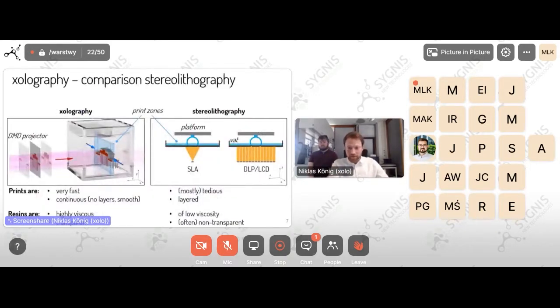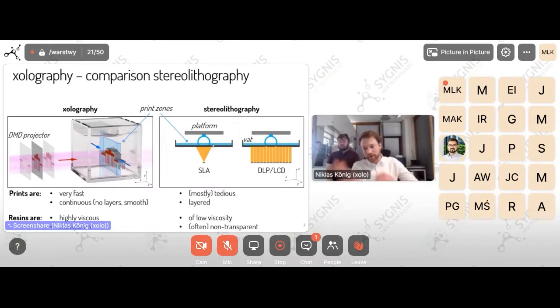Because when you compare it to standard stereolithography, you also have a vat here in blue, turned by 90 degrees, and the printing zone is actually between the platform or the built object and the surface of the screen or the membrane. And between the object and the membrane, you would usually have the printing zone where you cure your photopolymer, then you lift the platform or the object again, let the resin flow into the so-built cavity, and you dip it in again, cure your layer, dip it out of the volume again, and so on and so forth. And that's why you have a layered process for standard stereolithography, while in our case, we have a continuous movement of the printing zone through our photopolymer.